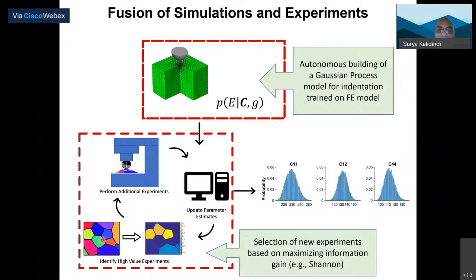In the experiment, when you go into your experiment in the lab, you say, oh, I have this sample and I have all these grains I could indent, but each indentation costs me something. So I have to decide which grain I want to indent. Then the system in the lab leverages this knowledge system and ranks the information gain: if you do an indentation here, there is a certain information gain. So in this particular case, it's saying you're much better off doing an indentation in this grain as opposed to some of the other grains where the information gain is very low.